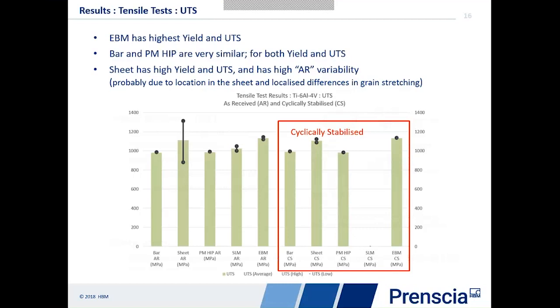So we've taken a tensile specimen and we've applied some, if you like, fatigue cycles, usually a couple of hundred cycles to it beforehand. That enables us to get shakedown, and then we do the test. The ones outside, to the left of that red box, are the traditional monotonic tensile tests. We put a coupon in the machine and we pull it and we do the tensile test. And what we can see here is the different UTS values for either bar, sheet, powder metal HIP process, selective laser melting, and electron beam melting.